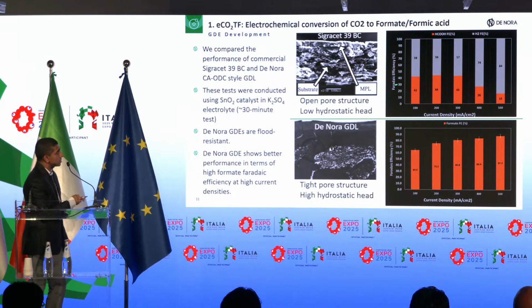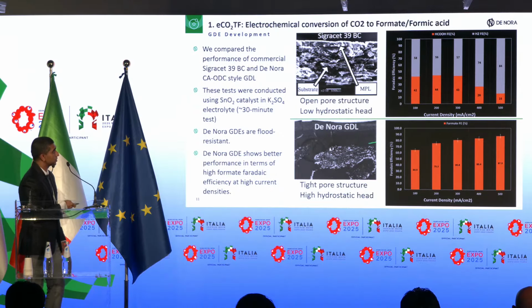The way to read these results: the y-axis shows the Faraday efficiency, and the x-axis shows the current density. What you see in orange is the formate Faraday efficiency. Clearly, when we use our De Nora GDL, we can push the current density to higher values while maintaining high Faraday efficiency for formate. We believe this comes from the higher flood resistance of our De Nora gas diffusion electrode.